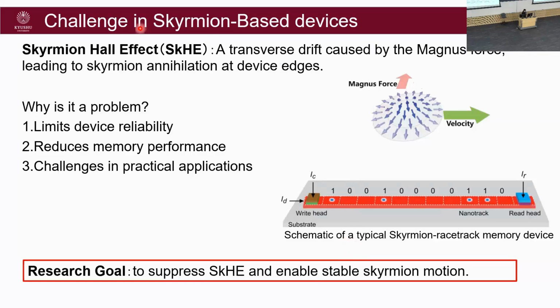When driving Skyrmion motion, its rotating spin structure experiences a magnus force, causing drift motion, and we call it the Skyrmion Hall effect, which will cause the Skyrmions to reach the device edge and annihilate, risking data loss. Our goal is to suppress the Skyrmion Hall effect and enable stable Skyrmion motion.